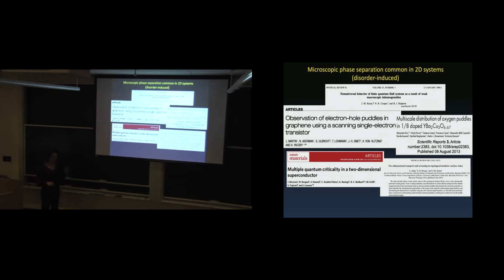And I feel like people seem to rediscover this every generation with every new material that comes out. So people saw this in quantum Hall systems. Microscopic inhomogeneities led to phase separation into Hall and non-Hall regions. In graphene, they discovered these electron-hole puddles. In a 2D complex oxide system, they found phase separation. In topological insulators, people found phase separation due to these microscopic disorders. So I think it's very, very common for 2D or low-dimensional systems to break up into different phases.